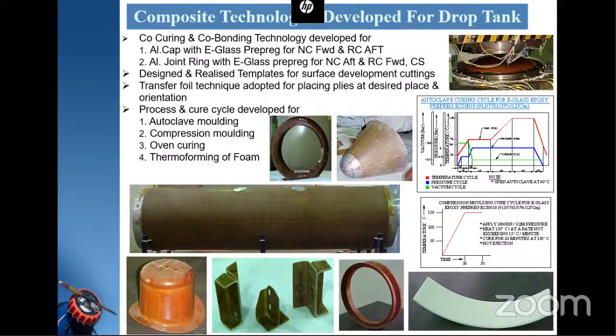Then we designed and realized templates for surface development cuttings, and the transfer foil technique was adopted for placing plies at the desired place and orientation. Process and cure cycles were developed for autoclave molding, compression molding, oven curing, and thermoforming of foam. Here you can see the shells are made in a variety of thicknesses. The tank is not of uniform thickness. It has varying thickness at varying places, and we have different thicknesses wherever there is a cutout requirement. We have placed extra fibers there to give reinforcement for the cutouts. Here we have developed varieties of shapes of components like hat sections, brackets, then tire kind of sections.